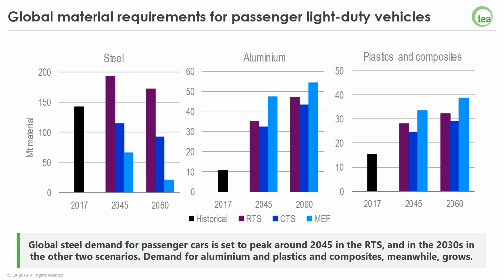The PLDV, the car fleet, goes from about 1.2 billion currently to 2.4 billion vehicles by 2060 in the reference technology scenario. So it's doubling. And despite that, you see only the 20% growth in steel. Note that in the midterm, represented here by 2045, steel demand in the RTS increases and thereafter peaks. In the clean technology scenario, a combination of reduced vehicle sales, rather than doubling by 2060, the vehicle fleet grows to 2.1 billion, so about a 75 to 80% increase.